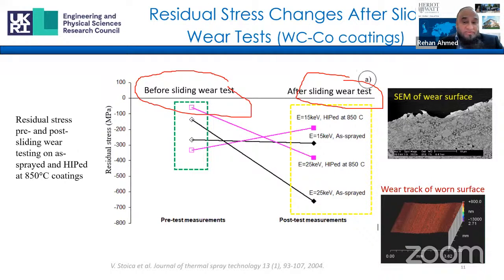using the synchrotron measurement. And although neutron diffraction is the gold standard of measurement for through thickness residual stress profiling, some of the near surface changes can be better captured by the synchrotron beam.